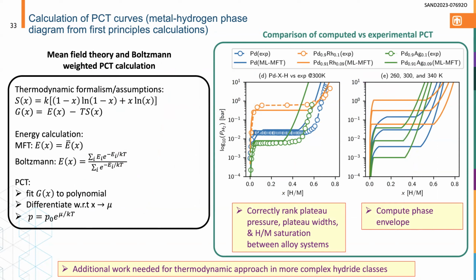On the left is just a simple thermodynamic formalism that, surprisingly, works pretty well for predicting the PCT curves in the system. So you assume an ideal mixing entropy, you can write out the Gibbs free energy, and the energy term comes from that GNN sampling that I showed on the previous slide. And there's multiple ways you can do that. You can do a mean field theory approximation or a Boltzmann sampling. But if you have that and you fit the Gibbs free energy to a polynomial and differentiate with respect to chemical potential, that gives you the pressure, and then that allows you to construct that PCT curve on the right.